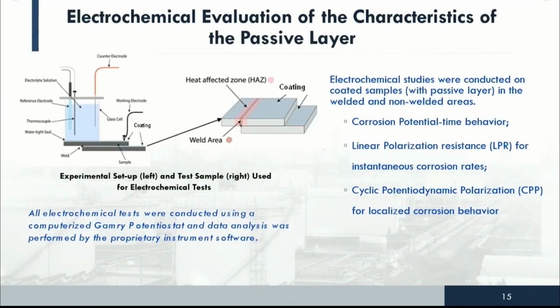Now we know there is an effect. If you do welding, you're going to have an affected zone, you're going to change the morphology of the coating, and you're going to change the microstructure of the base metal. For the first time, I think, in my lab, I've used electrochemistry to evaluate the characteristics of this layer. Due to the nature of this coating being a little bit porous, we could do that.